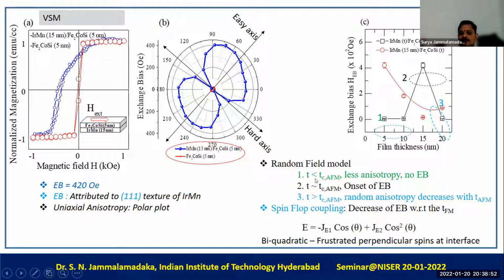Essentially, when the thickness of the film is less than tC, since there is less anisotropy, there is no exchange bias. However, when t is of the order of tC, the onset of the exchange bias happens. But when t is greater than tC, the random anisotropy decreases with the antiferromagnetic layer thickness. And the decrease of the exchange bias can be explained based upon the spin flop coupling.